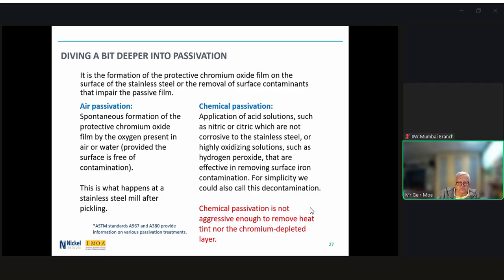If they've annealed a piece of stainless steel plate, they immerse it in a bath of pickling solution and leave it there for a designated amount of time. They remove it from the bath, rinse it with clean potable water, and the surface then spontaneously forms by reaction with the oxygen present in the air.